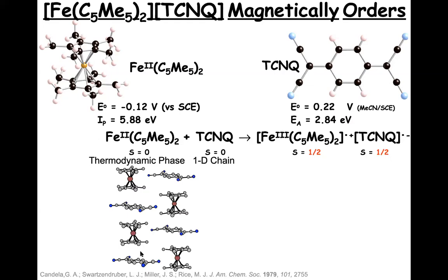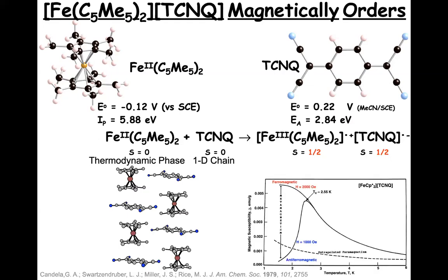And it totally was a failure with respect to conductivity. It's a poorly conducting material, not an organic-based metal. But when we studied the magnetic properties of it as part of our study and measured the susceptibility at 1,000 Gauss applied field, it rose up, had a maximum of about 2.5 Kelvin and dropped down towards 0. Indicative of an antiferromagnetic type of system, which is fine.